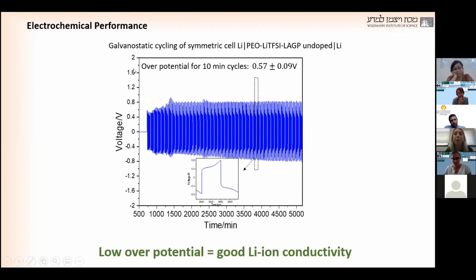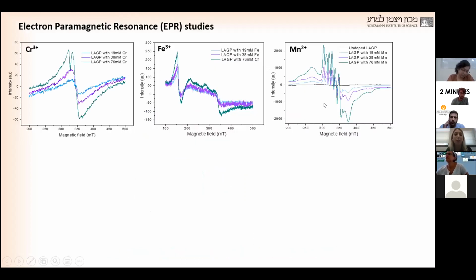So for that, we did an experiment of galvanostatic cycling of a symmetric cell. This means that we have the composite, and the electrodes, the anode and the cathode, are from lithium metal. So in this way, we're supposed to get a voltage that's equal to 0. But according to the resistance of the composite, we will get overpotential. So as long as the overpotential is lower and near to 0, the higher the lithium ion conductivity. And we can see here that we get a really good result, 0.57 of the overpotential.